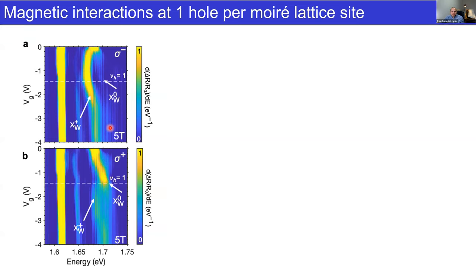So for sigma minus, this top graph here, we see the peak that we label the X plus, which is the positively charged exciton, intralayer exciton peak, emerges just past zero doping. So it starts there, and then it continues with a high degree of spin polarization, which we expect due to the band alignment in our system. And the other Zeeman transition is barely visible.